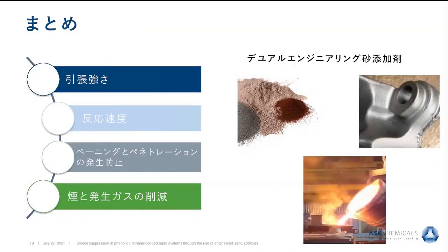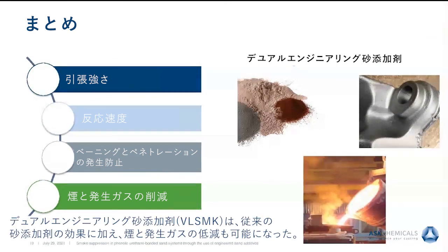So in summary, I will say we have successfully developed a dual engineered sand additive that can produce high quality castings. It can reduce the smoke. And on the other hand, the other properties of the phenolic urethane no-bake mold and core technology can be adjusted to make this whole process work smoothly and without any issues. So far, the tensile strengths can be adjusted, the reaction speed can be adjusted, and the elimination of the veining, metal penetration and improved surface finish was accomplished. And more exciting, we had the smoke and emission reduction, which will be the new benefit from the use of this sand additive.